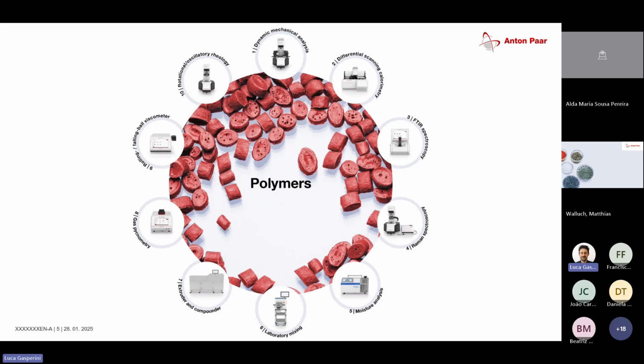Then processing, we have different scales of processing. The smallest we have is a mixer with 50 milligrams of sample volume where you can test formulations, and then you can also scale up to twin screw or single screw extruders in all different shapes and sizes. They go from 60 grams per hour all the way up to 100 kilograms per hour, depending on what you really need. Then the last two are also something new.